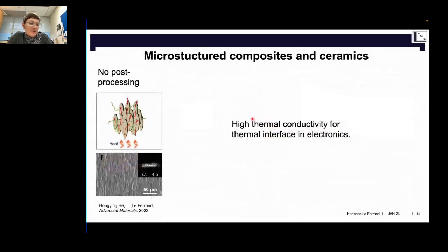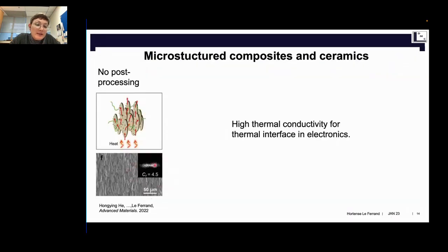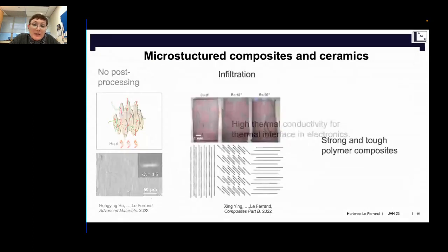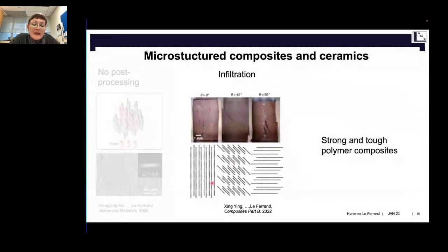Okay, so now we have our microstructures aligned. So how do we turn it into a composite and a ceramic? Either you use it as such without post-processing and you get a material. So here we did that using boron nitride platelets to make high thermal conductive materials for electronics. You can also infiltrate it, and then you can make strong and tough polymer composites. So here we varied the orientation and showed that, well, the nacre-like is indeed the toughest.